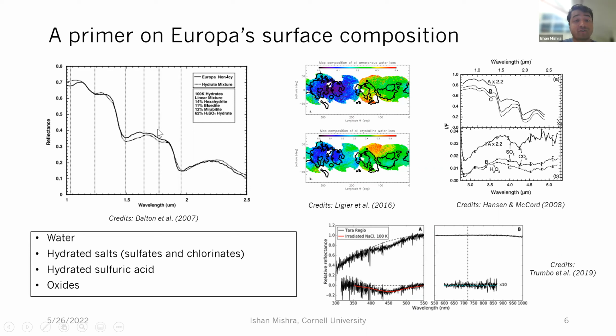Then we have a lot of salts. In this figure, the bold line is the actual spectrum of Europa, and the dotted line is a simple linear mixture of different kinds of sulfates, hydrated sulfates. The general nature of the spectrum and the general features of the water band match our expectation from hydrated salts. And there is also hydrated sulfuric acid that has been detected and shown from lab experiments to be a dominant component on the surface.